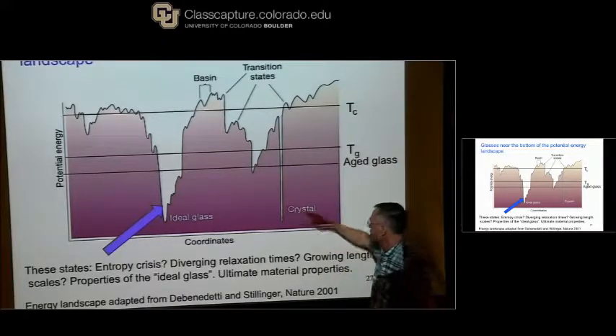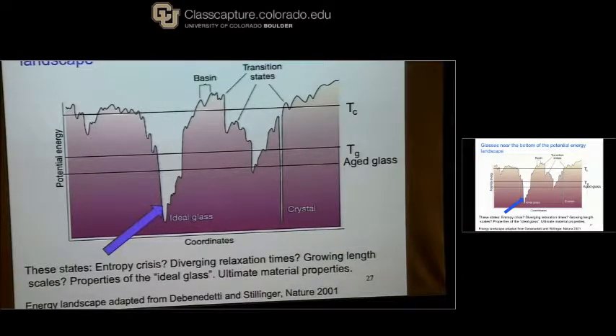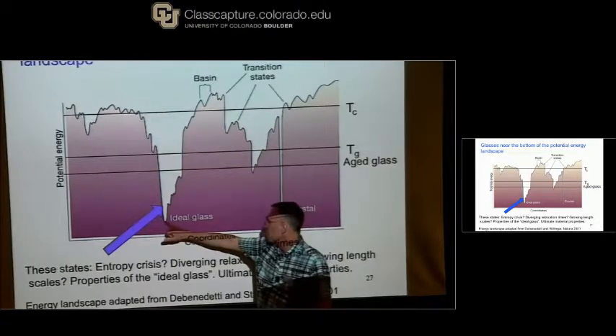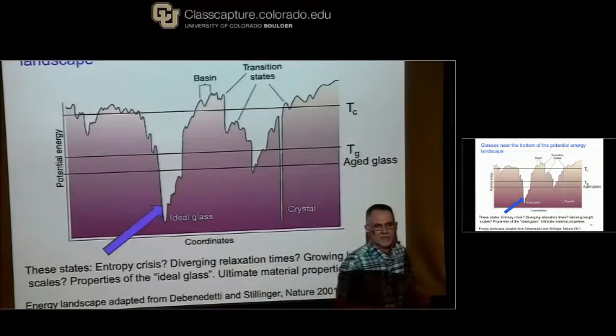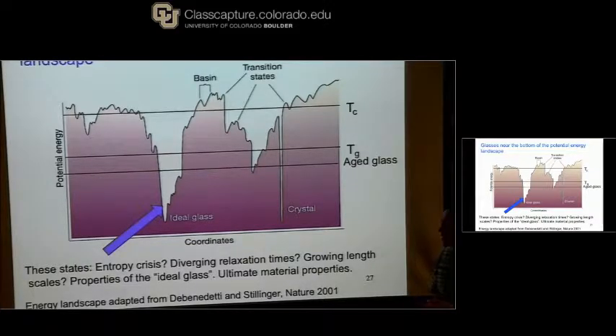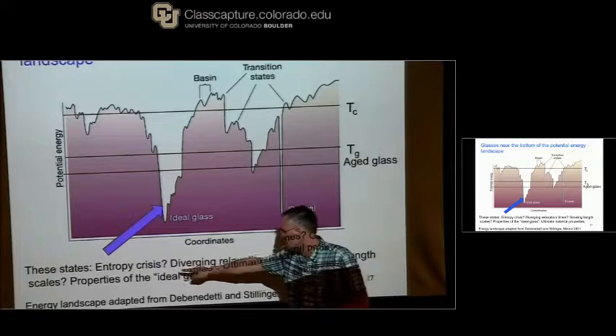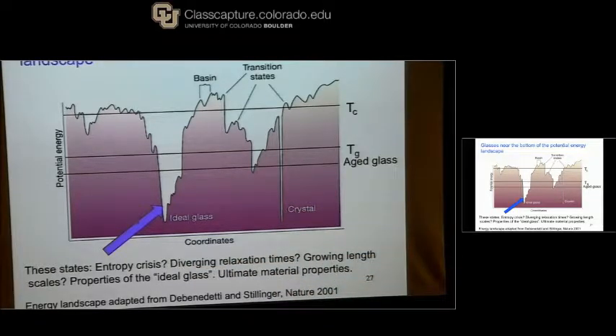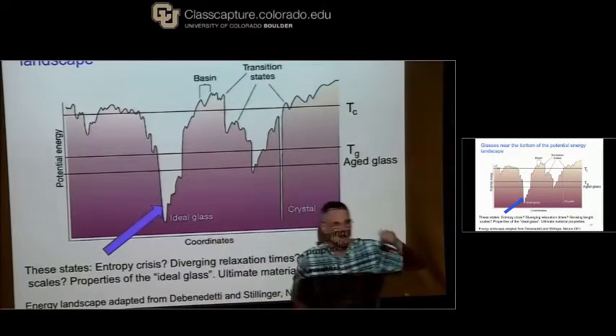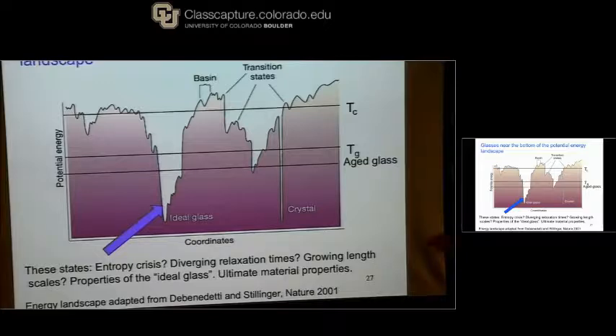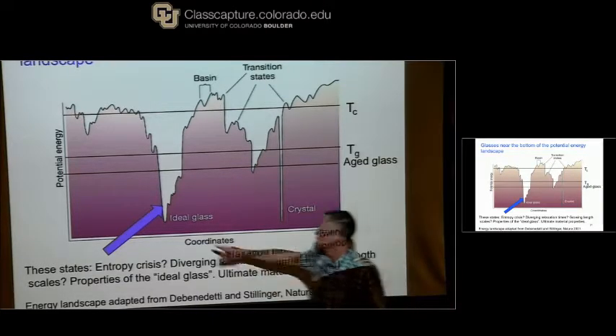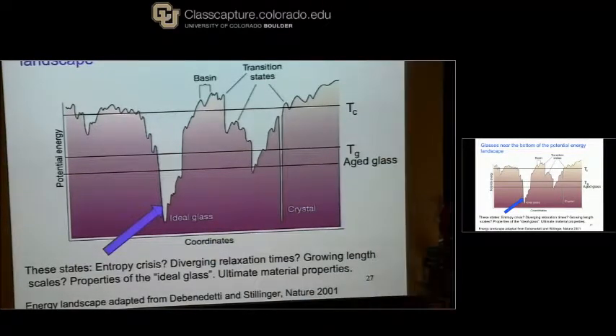If we stay away from the crystal and we go to the bottom of the amorphous part of the potential energy landscape, what are these states like? The traditional thing to call this state right here is the ideal glass. It's the bottom of the amorphous part of the potential energy landscape. Let me just point out all the things that are interesting about states down there. This whole business about the configurational entropy going away has to do with how the number of states is getting smaller as we go down to the ideal glass. And so somehow that information is encoded here. Whether relaxation times actually diverge or not is somehow encoded in the barriers that are down there at that part of the landscape.